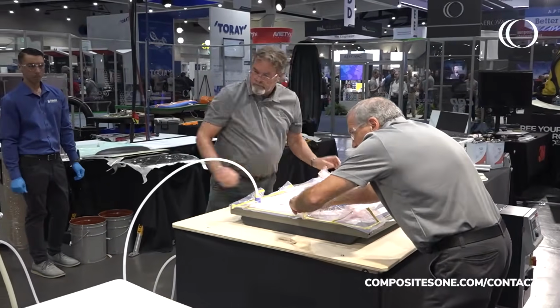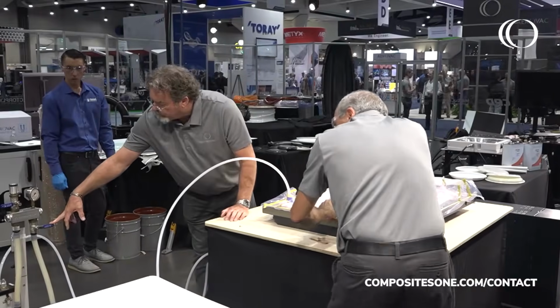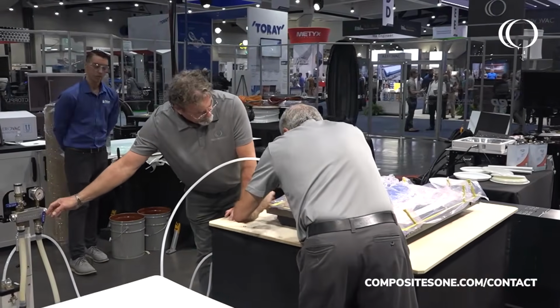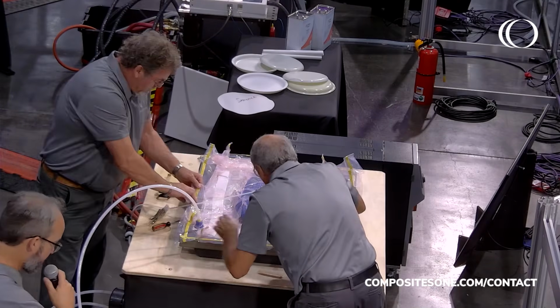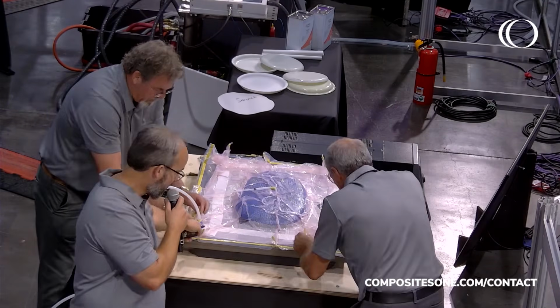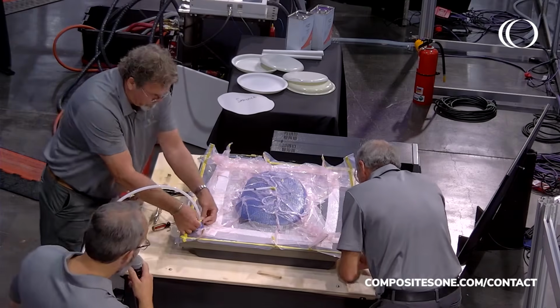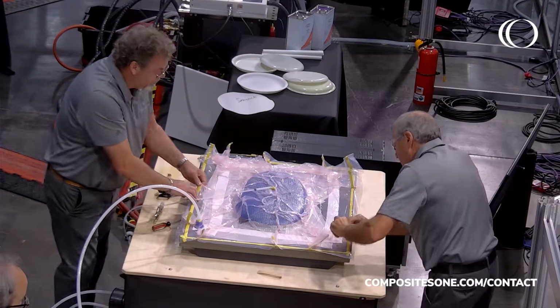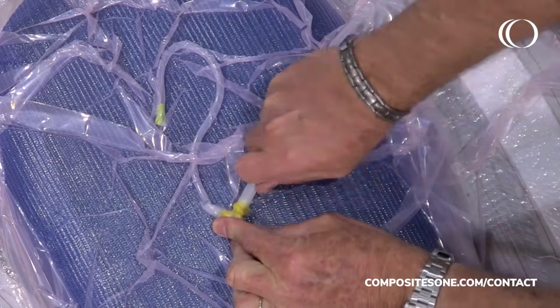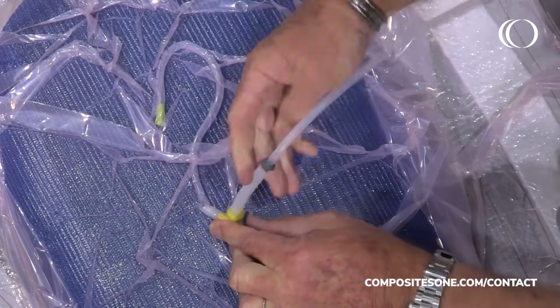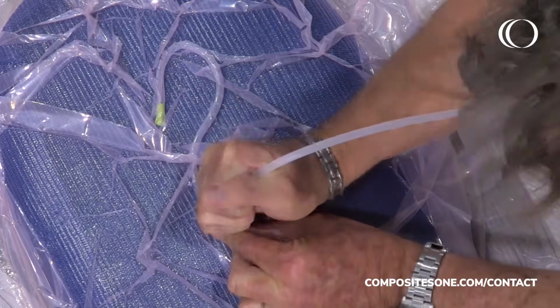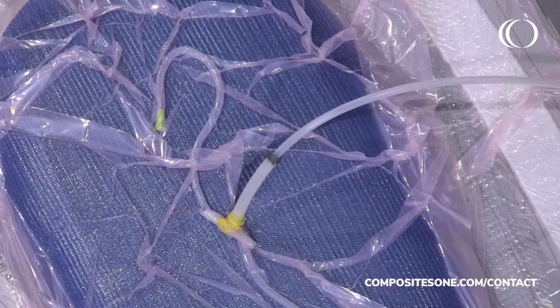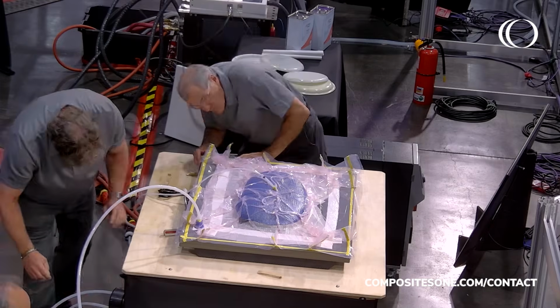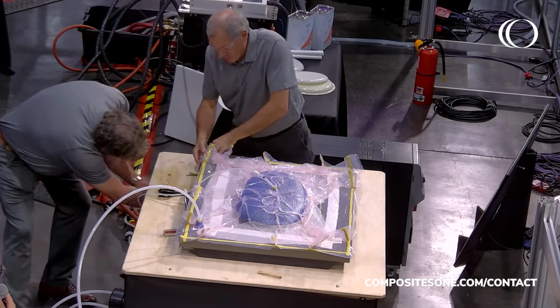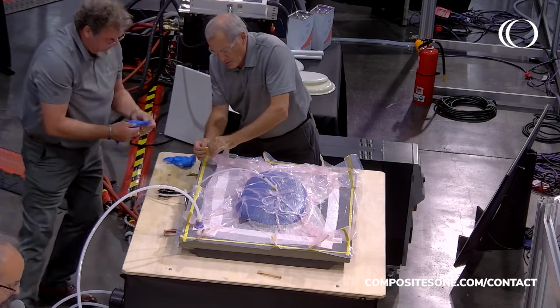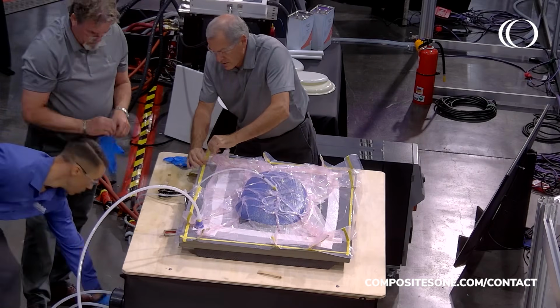So you'll notice one of the other features we have is we're using a resin infusion connector. So it's this blue little cone-shaped piece in the part. And that goes on underneath the bag, sits on top of some breather, and allows us a nice connection to our vacuum hose in this case. It can also be used on the feed side to introduce resin into the part. And it's made out of polyethylene, so it's reusable, and can be used several times in the process.